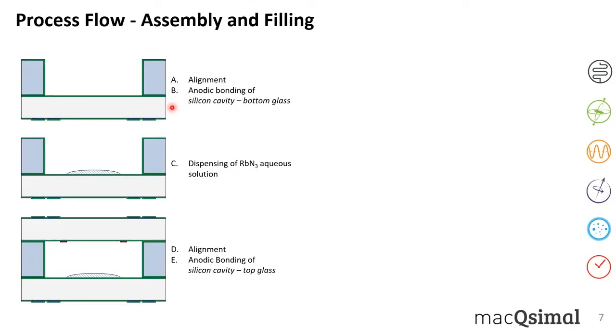So after this, we make a first bonding. We have to align the wafers. Then we bond the bottom glass wafer to the silicon cavity wafer by anodic bonding. And this, what we call then a preform, we send out to an external partner who makes the dispensing of rubidium azide diluted in water. And once we get it back,